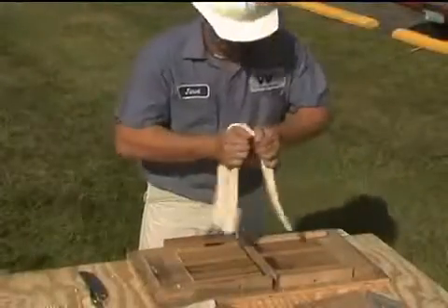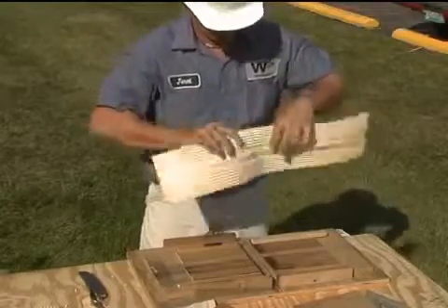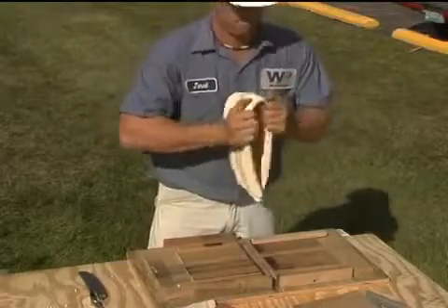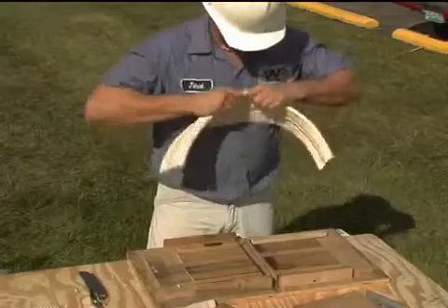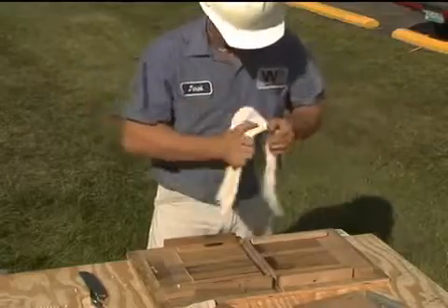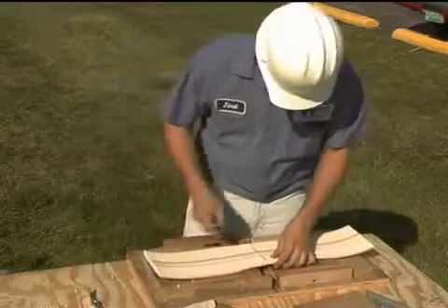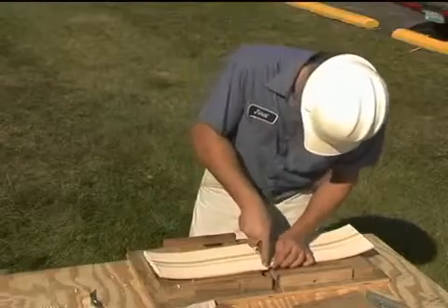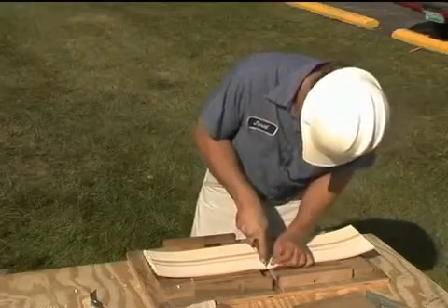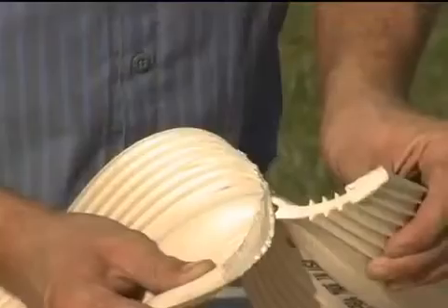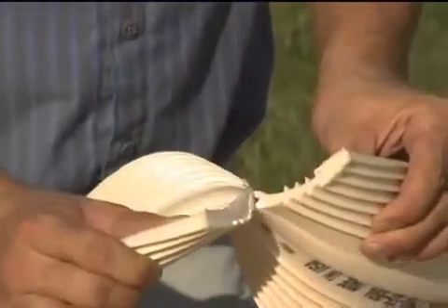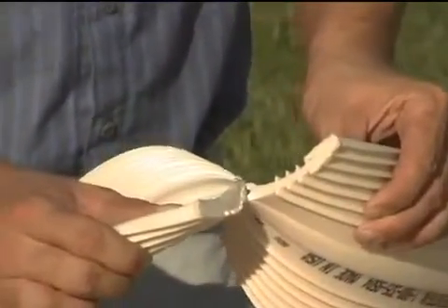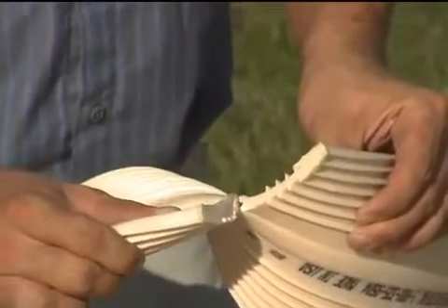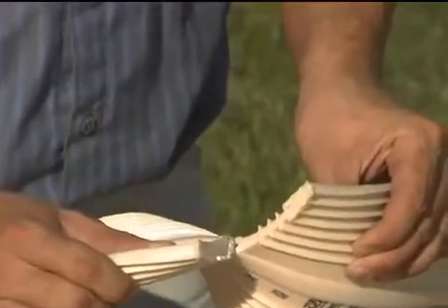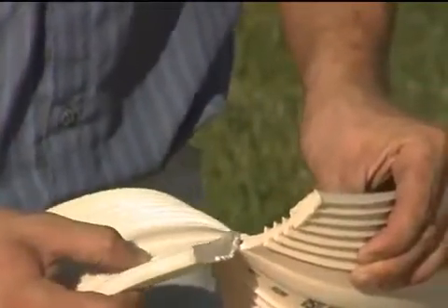It is also a good practice to perform a destructive sample weld at the beginning of each day to ensure that the proper technique is being used and that the welding iron is working properly. This can be done simply by making a straight butt weld and then cutting the water stop splice along the axis of the water stops at multiple locations to expose the inside of the weld. Other than the melted flashing of PVC at the splice, the center of the water stop weld should look the same as the unmelted cross-section if the weld is sufficient. No porosity and no difference in color or consistency.